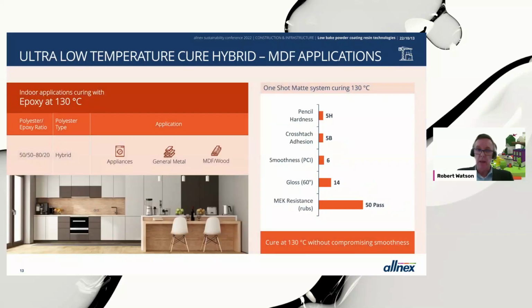If we go to the next step, to 130 degrees centigrade, this is where we get into the realm of ultra low bake. And here, this is with a polyester curing with an epoxy resin. And there's examples across all the ratios that can be used. Typical applications are in domestic appliance and in general metal. But now we start to open up MDF and wood.